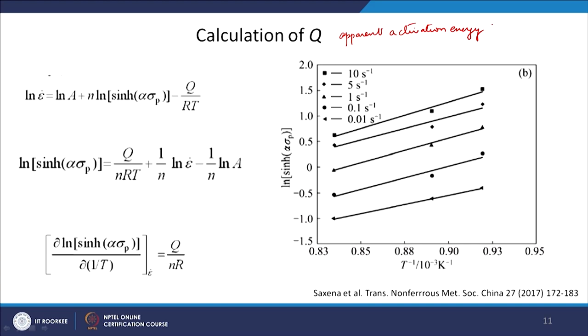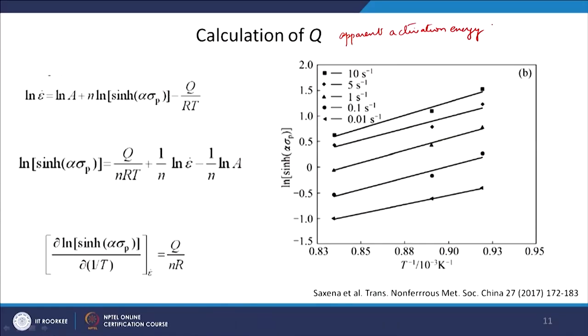The reason is that the microstructure is continuously changing during the deformation, and these are not activation energies calculated from one specific mechanism. We are trying to predict a mechanism using the activation energy, so the microstructure is not going to be a stable microstructure. For example, you are deforming at different temperatures here. Earlier, if you remember, in dynamic recrystallization, as you change the temperature, the flow curve changes from a single peak showing discontinuous dynamic recrystallization to a multiple oscillating peak kind of stress strain curve.